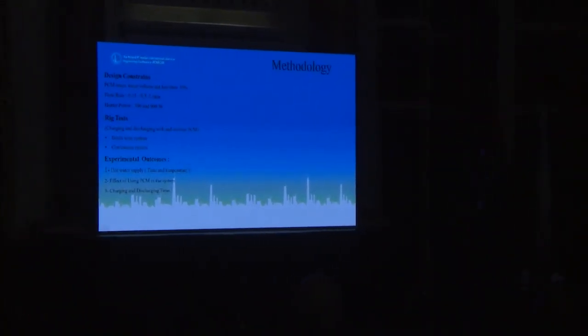Now, let's talk about our design constraints. Our design constraint is the ratio between the phase change material mass and the water mass in the tank, not less than 30%. The flow rate of the water is between 0.25 to 0.3 liter per minute, and the heat power, we adjust the electric heat power around 700 to 900 watt due to different readings of solar radiation in Palestine. Now, what we study in the test, we study the charging and discharging procedure.